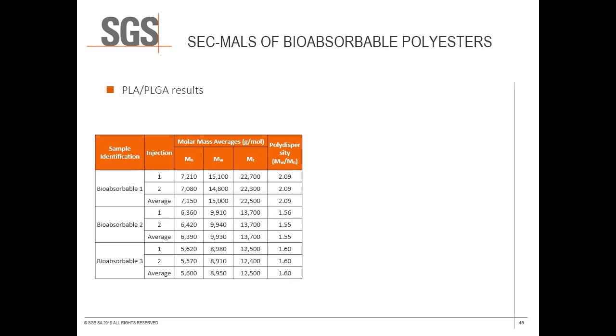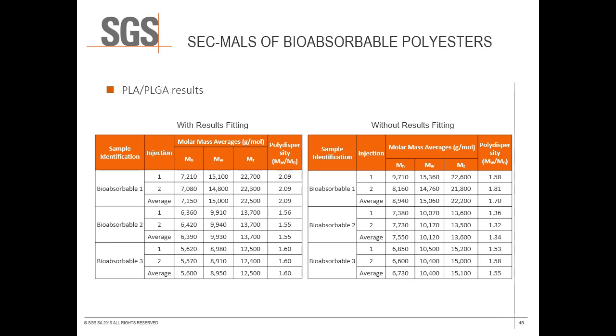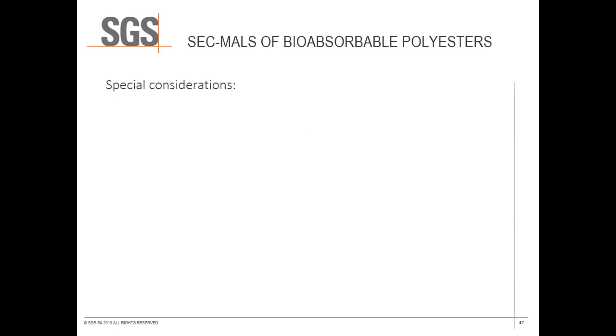In a comparison of the results obtained with and without results fitting, the results fitting proves to reduce deviation between replicate injections and prevents the low signal in the front and tail of the peak from causing falsely high calculated molar mass results. The difference is as high as 20% in some cases, particularly for the number average. In summary, some special considerations must be made for the analysis of bioabsorbable polyesters, as some polyesters may contain repeat units of various configurations and are often copolymers of more than one type of monomer. This poses challenges for solubility and differential refractive index increment accuracy.